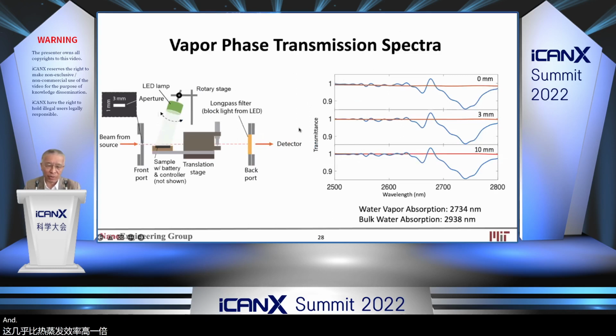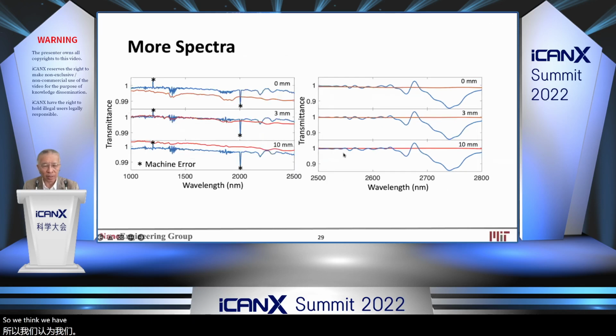And we still want to see our silver bullet, the vapor spectrum. So this is measuring the transmission of the vapor. In this case, we actually heat up the water, because when we do not heat it up, we cannot measure it. The cluster is too close to the surface. But we heat up the water, and we measure: the red is when light is off, the blue is light on. You can see when light turns on, the absorption happens very close to the water vapor absorption, but it's continuous. That means it's more than one water molecule, not a discrete water molecule. Those are the clusters. So we think there is more spectral information, and all this is consistent.